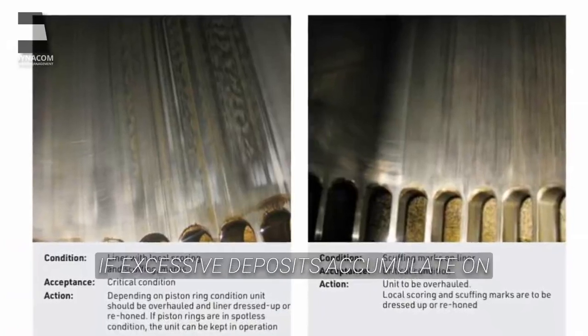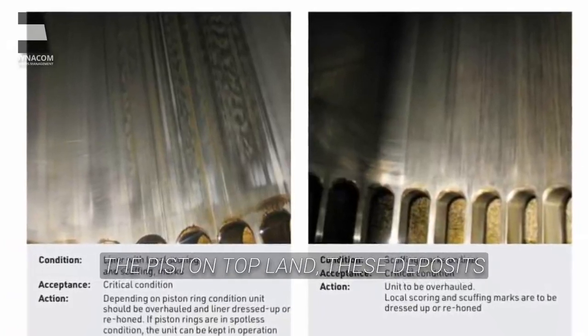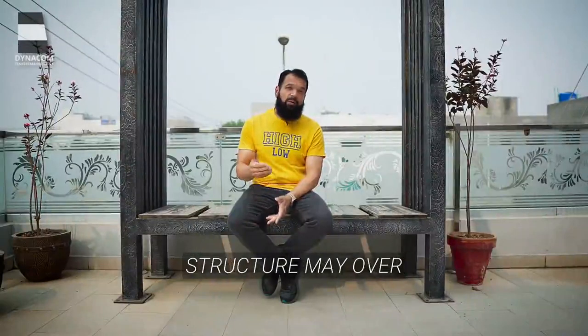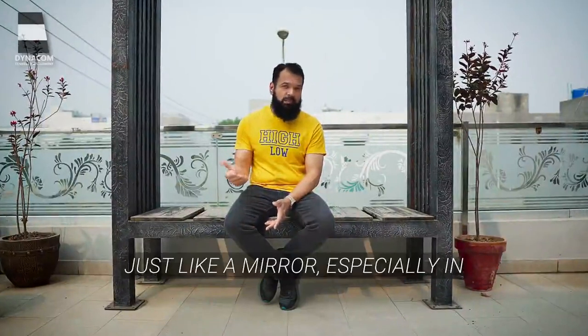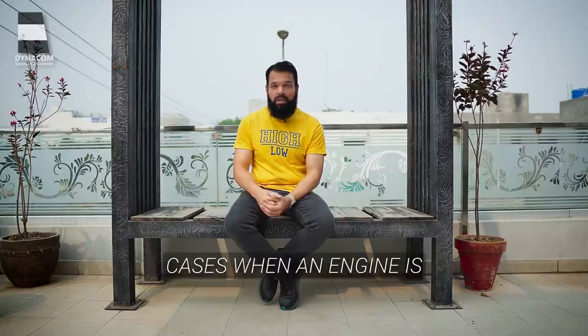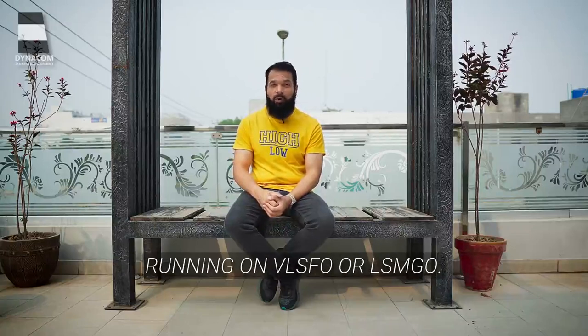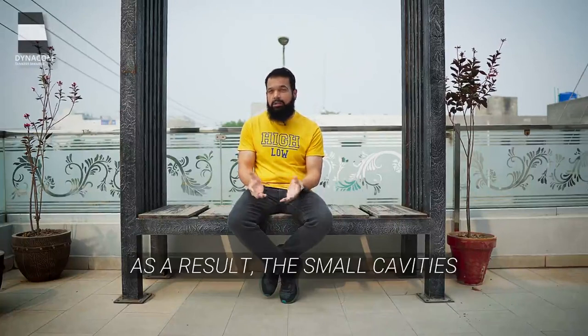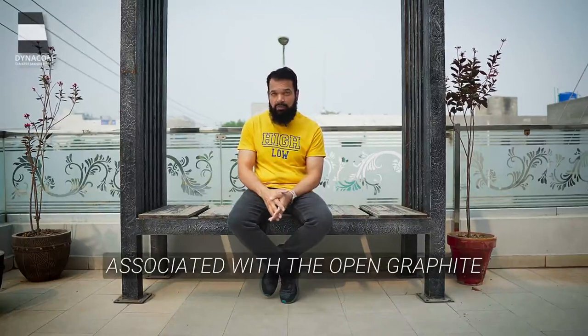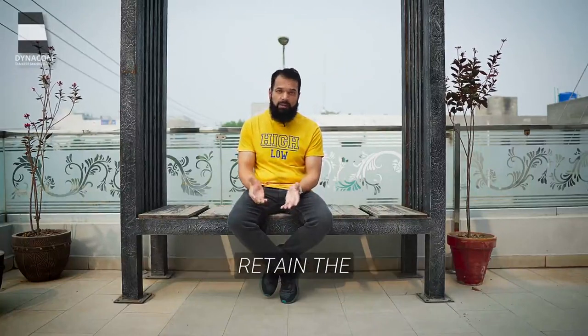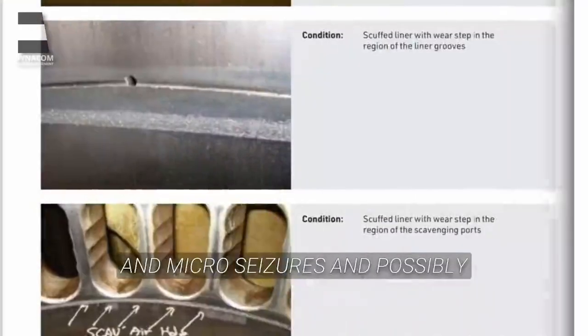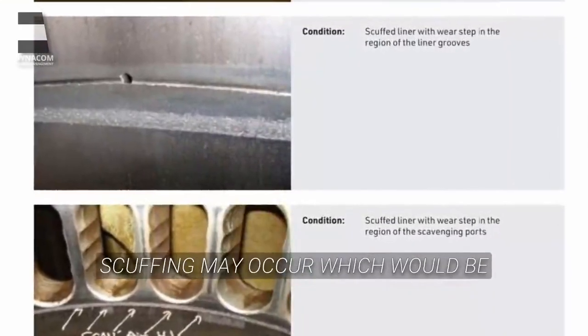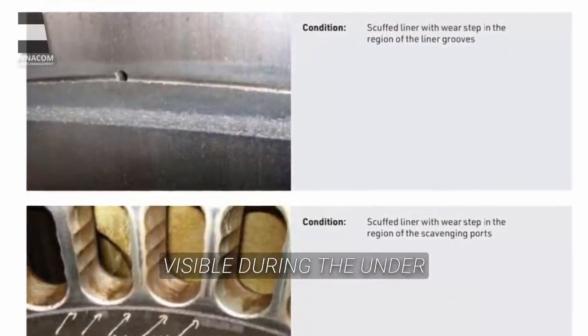If excessive deposits accumulate on the piston top land, these deposits can polish the liner surface and the running surface structure may over time become smooth, just like a mirror, especially in cases when an engine is running on VLSFO or LSMGO. As a result, the small cavities associated with the open graphite flakes may no longer retain the lubrication oil sufficiently, and micro seizures and possibly scuffing may occur, which would be visible during the under piston inspection.